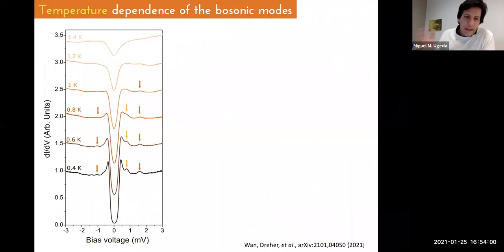So the first thing we did was to study their evolution with the temperature, because if they are related to superconductivity, they should be there in the superconducting state and of course disappear with it. So here I show you the evolution with temperature. Here we increase the temperature of the sample, and we start having three different modes, two on this side and one on this side.